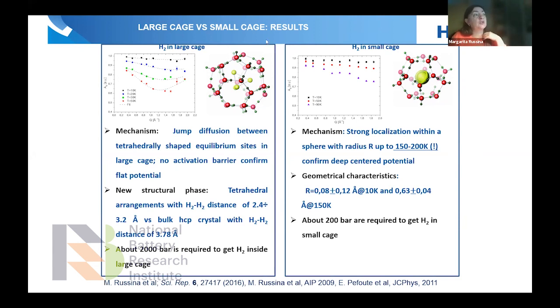Interesting is that to place the hydrogen with this localization, this landscape with a deep minimum inside the cage, working like a molecular pump, you need 200 bar, but to place hydrogen in the large cage with a flat potential, you need 2000 bar. So basically the confinement works like a pressure. It allows you to put the molecules inside there and remain there much more stable at much higher temperatures.